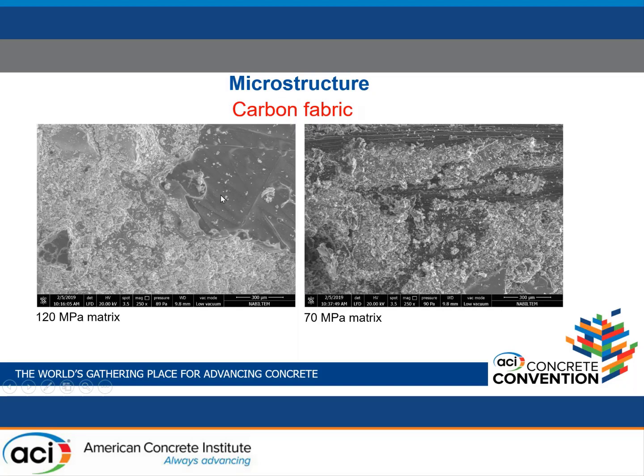Over here in this slide, you see the same comparison for carbon fabric. This is the 120 megapascal matrix, and this is the 70 megapascal matrix. But the difference here from the previous slide is that you see more mortar residue on the low strength matrix than on the glass fabric. The reason for having this mortar on the carbon fabric is the sand particles on the SBR coating that increase the bonding.